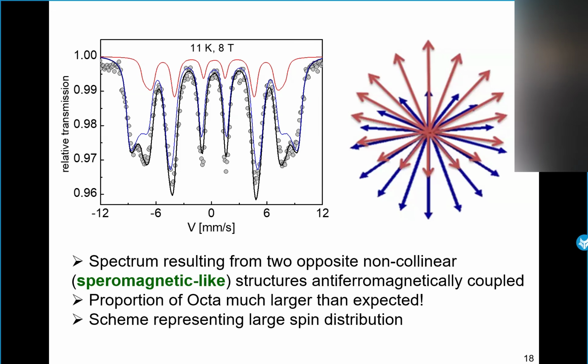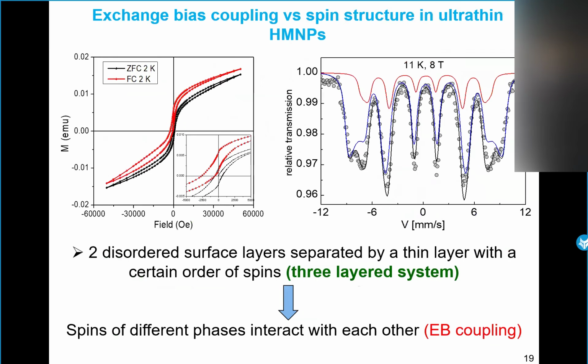We arrived to reproduce the experimental spectrum, but there are some differences between the model and the experimental one. We arrived to reproduce this difference easily by introducing a new minor subspectrum corresponding just to ferrite, ordered ferrite. So finally, we can model our structure as three layers: two disordered surface layers separated by one layer with a certain order of spins.